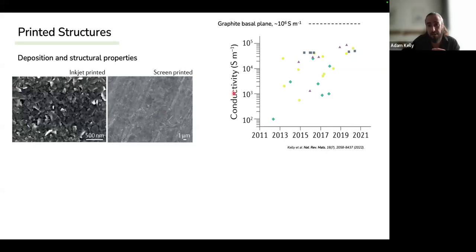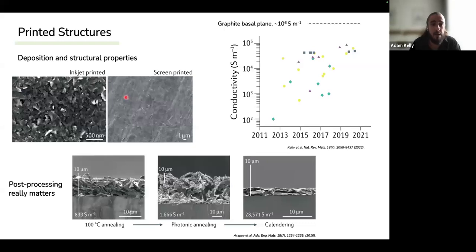If we look at the conductivity as a proxy for the quality of the network itself, what we notice is that since these papers started being published back in about 2012, regardless of deposition method, inkjet printed or screen printed, the conductivity is trending towards the graphitic basal plane. So we've all these improvements in conductivity, and it doesn't matter which way you deposit it. And this is because if we look at it, after you printed and deposited your network, the post-processing is really important.